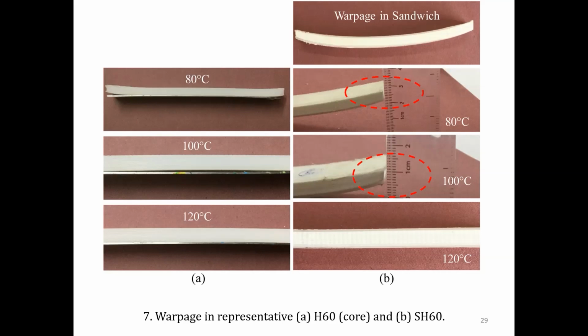Once you look at the CTE values, based on their difference, you need to increase the chamber temperature so that the temperature gradient is in a very narrow range to have multi-material printing. Similarly, we also did here with the help of CTE. So this is about only the core. You can see 80 degrees, 100 and 120, it was perfectly flat.